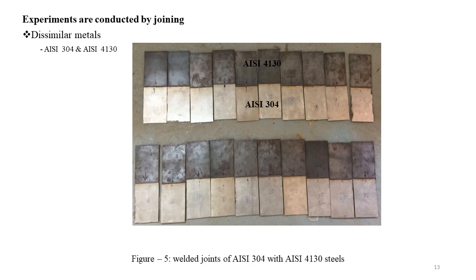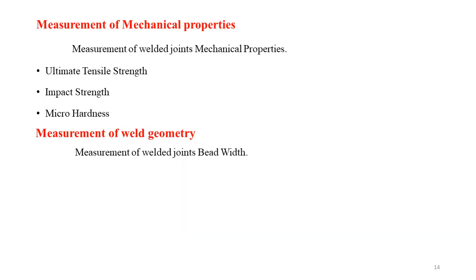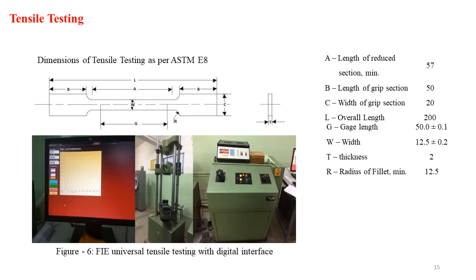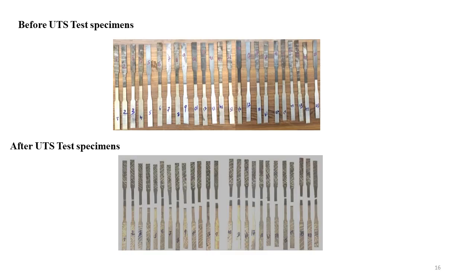We want to observe here that in the weld zone, the materials are completely merged. After welding, we want to measure the mechanical properties and weld geometry. For weld geometry, bead width is measured. A tensile test is conducted to measure the ultimate tensile strength.